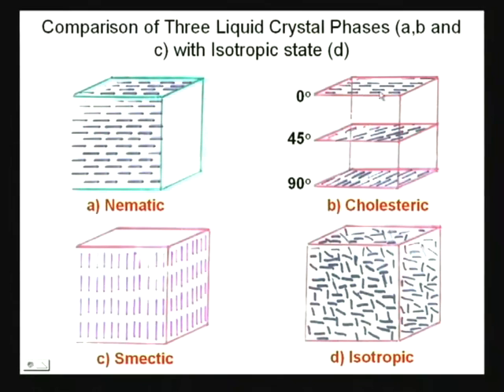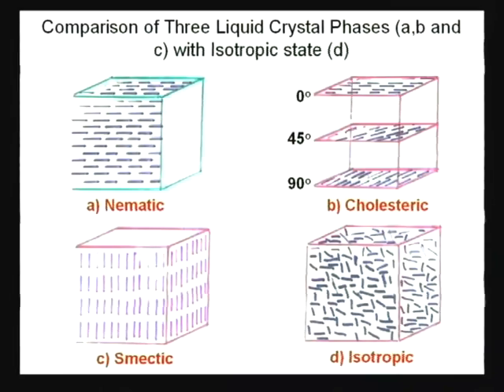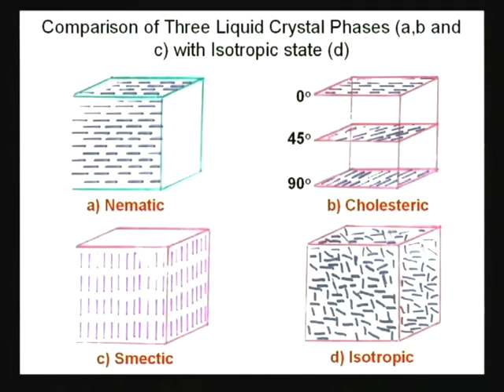Now, as I told, if you have layer like structures like this, in one layer alignment is in this direction, in another layer alignment is in this direction, in another layer alignment is in this direction. So, this is called cholesteric, and you can consider this kind of cholesteric arrangement as molecular composites. You understand, molecular composites, where there will be some dispersed phase in a dispersion medium, which is continuous phase matrix. All right. So, you can consider this as molecular laminates. So, if we can develop sophisticated conditions of polymer synthesis, we can synthesize molecular laminates with cholesteric liquid crystalline phase structure configuration, and those can provide high performance properties.